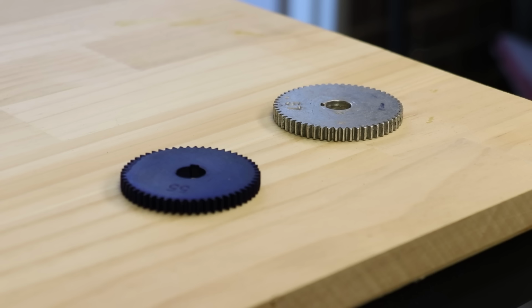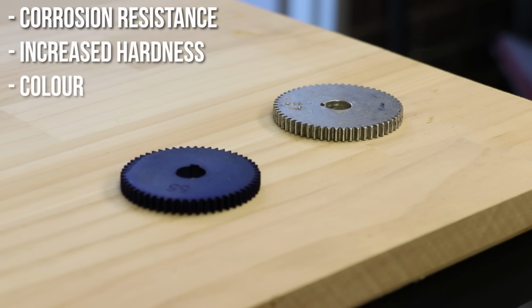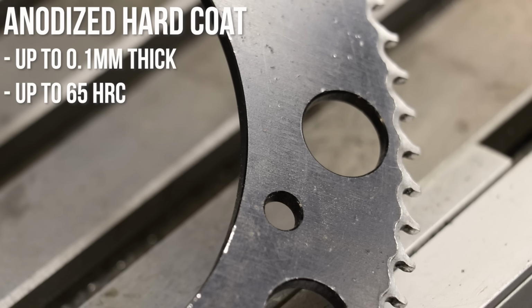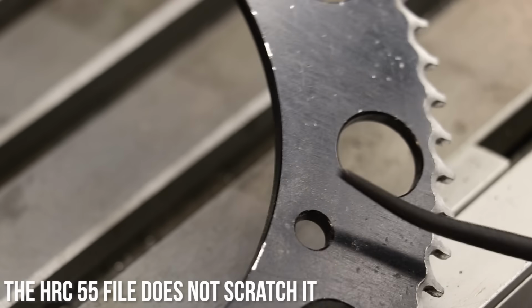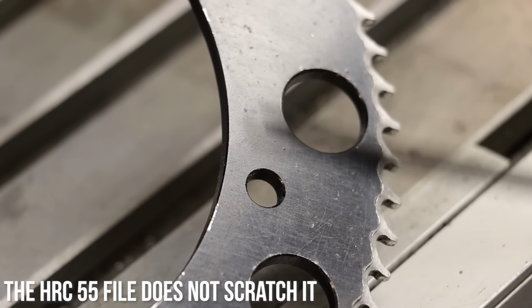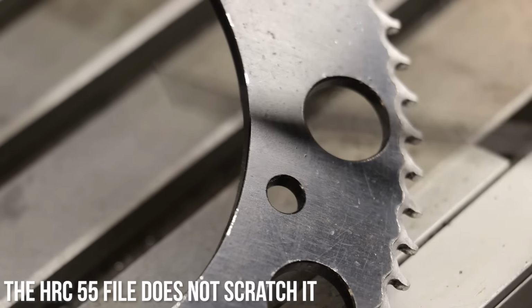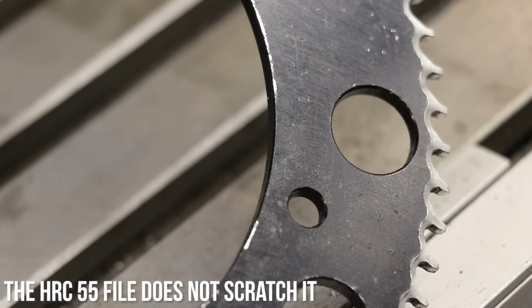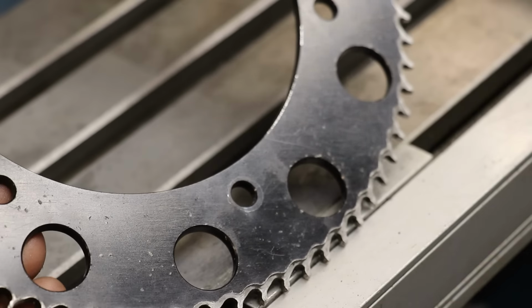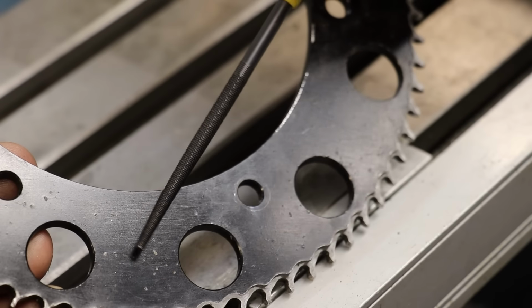I'm not saying that it's not good enough, but if you want increased resistance to corrosion, increased surface hardness, or adding colour to the part, it will need to be anodized, and the increase in hardness is really nothing to scoff at. Anodized hardcoat, which we found on the sprocket, can easily be 0.1mm thick and reach upwards of 60 to 65 Rockwell C in hardness, which is knife level of hardness. According to the hardness testing files, these were easily 55 Rockwell C hardness and just about 60, which is crazy hard and scratch resistant. Although because it is very brittle and the layer is so thin, if you push down hard enough, you will cause it to crack and you can even hear it cracking.